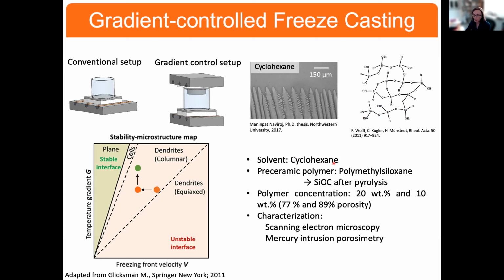So the experiments that I'm going to talk about use cyclohexane as the solvent. And as I said, we use polysiloxane, in this case polymethylsiloxane, as our pre-ceramic polymer. After it is pyrolyzed, we are left with silicon oxycarbide. And we looked at this with a few different concentrations.